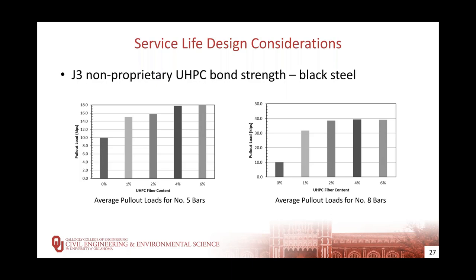Again, the 0% fiber specimens were included to obtain a baseline value, but many of the 0% fiber specimens still failed due to splitting, even with the short embedment length. So, adding even 1% fibers significantly increased the pullout strength. Adding additional fibers increased the pullout strength in general, but little gain was seen after 4% for the number 5 bars and after 2% for the number 8 bars.